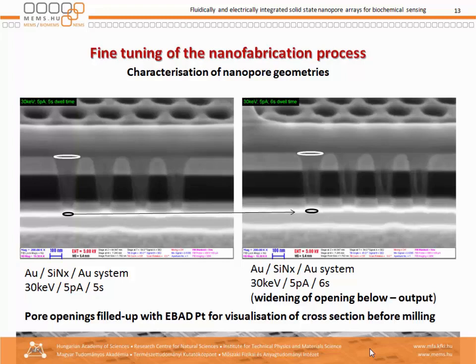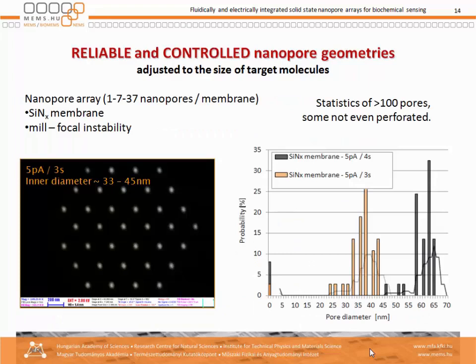This is the cross-sectional view of the drilled nanoholes. The nanopores can be opened up by using elongated drilling time with the same drilling current. The electrolyte penetrates from the upper side to the bottom side, so finally the cross-sectional view will be visible on the bottom — this was a specially prepared specimen for visualization. We use a nanopore array; however, the distribution of hole diameters is broader or narrower depending on the specificity of the drilling process, and we can change the mean pore diameter by increasing drilling time.